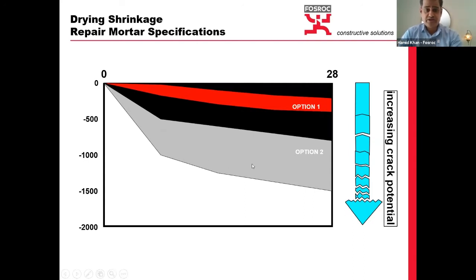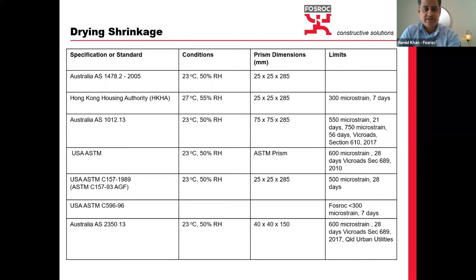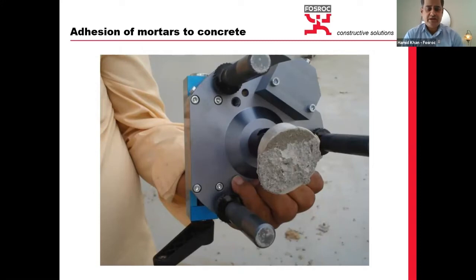So as you can see from this graph, this is in microstrain. As we go more than 500 microstrain, the potential for cracks increases tremendously. So the best is to look at this as number of days from 0 to 28. Around 300 microstrain is a typical value at 7 days, and 500 to 600 microstrain are typical values for 28 days or 56 days. That is acceptable. But if we go more than that, you can see the higher the shrinkage microstrain values, the more potential for cracking. So it's directly related to the drying shrinkage, and it's very important to have that property mentioned on the technical data sheet.